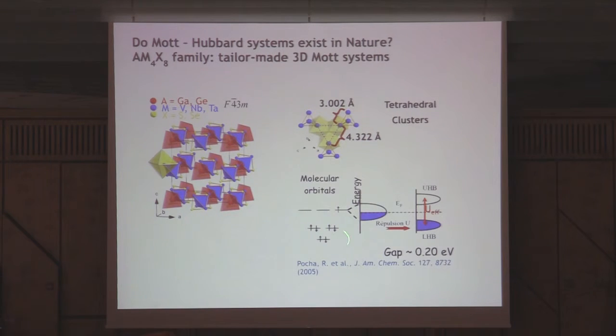So as I said, you have your molecular orbitals, you put your electrons, and you find out that you have 1 remaining electron in a T2G band because it has a cubic lattice, it's an FCC. So you have T2G bands being the conduction bands there with 1 remaining electron. You would expect to have a partially filled band, therefore a metal. But in real life, these systems are insulators with a gap of a fraction of an electron volt.